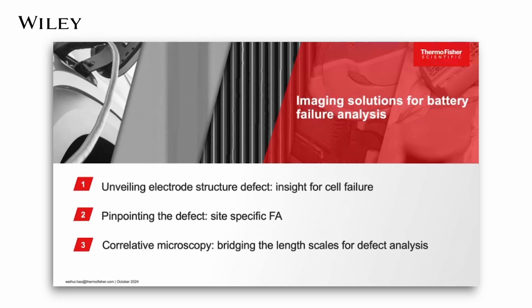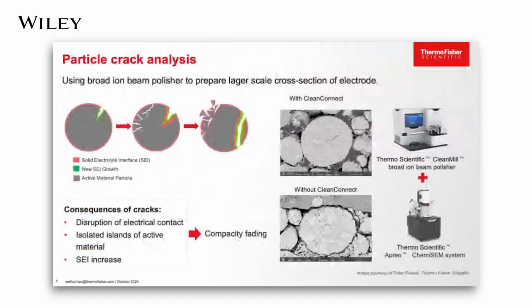identification of crack in cathode material. Particle cracking in cathode material is a significant factor contributing to capacity fading in lithium-ion battery. Repeated charging and discharging cycles may cause volumetric changes in cathode particles and lead to mechanical stress and eventually cracking of active particles. The crack could lead to loss of active particles by isolating portions of active materials and disrupting conductive pathways within cathode, increasing internal resistance and exposing new surfaces to electrolyte, which can lead to unwanted side reactions and eventually lead to the capacity fading of the battery cell.